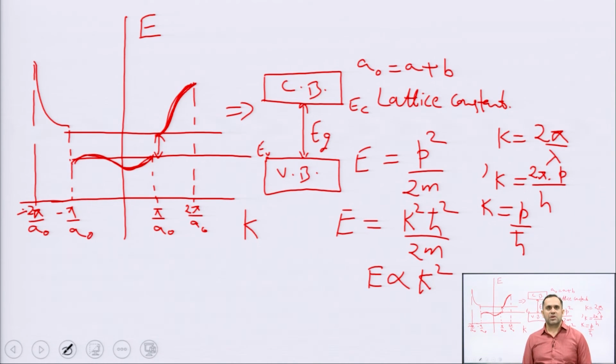So, this is how you can mathematically relate to the formation of energy bands in a crystalline solid. Now, this value of Eg will help you to differentiate between different types of materials. A value of Eg equal to 0 signifies a metal, a very large value of Eg signifies an insulating behavior, and an intermediate value of Eg specifies a semiconductor. And among semiconductors, the range of Eg tells you how much energy may be required for electrons to jump from the valence to the conduction band.